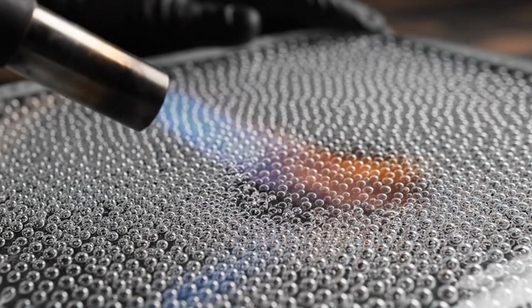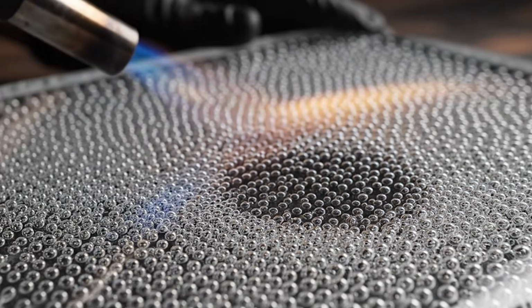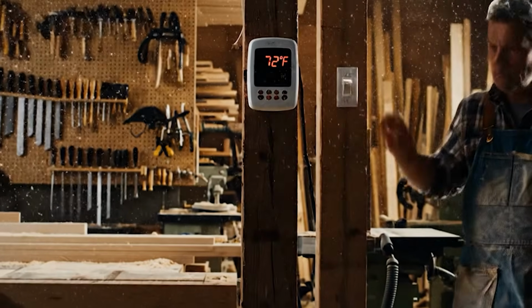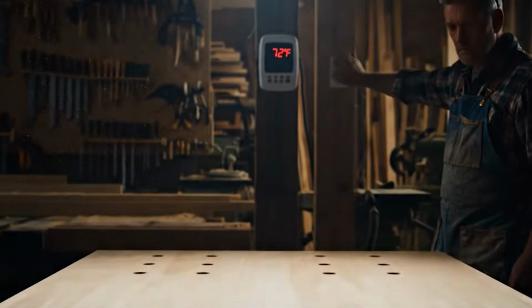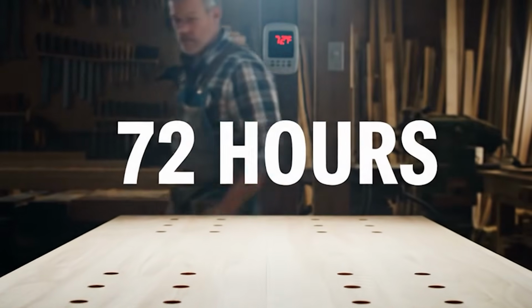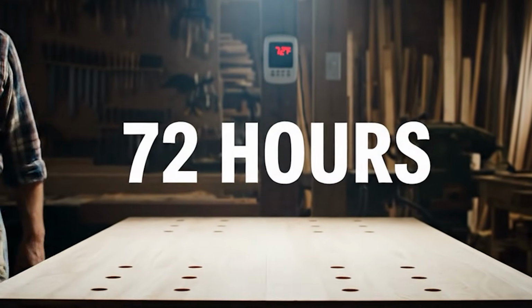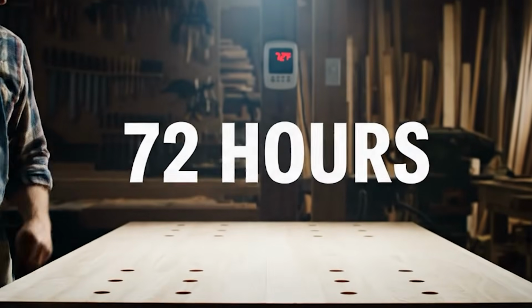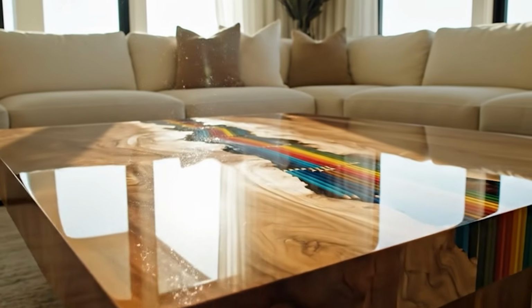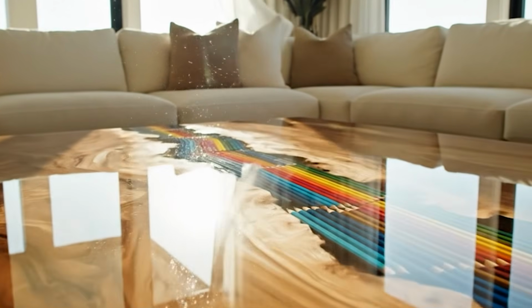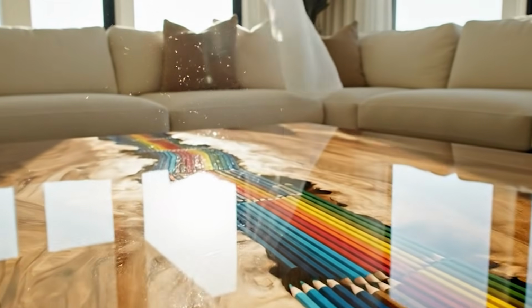Most deep pour epoxies take between 24 and 72 hours to fully cure depending on temperature. I keep my shop at around 70 to 75 degrees Fahrenheit for epoxy work. Too cold and it won't cure properly. Too warm and it can exotherm and crack. Once the epoxy is fully cured and rock hard, it's time to demold, flatten, and sand.